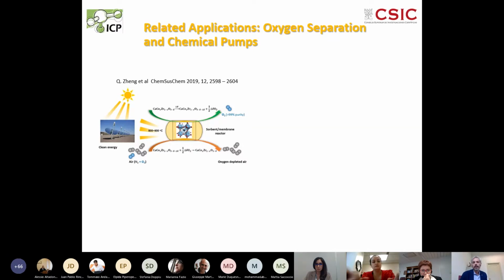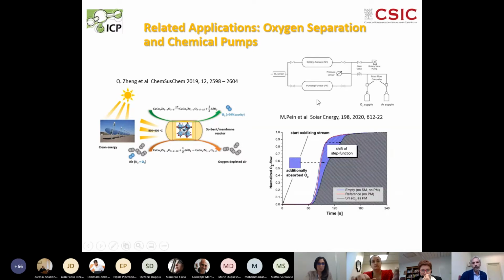And we can also take advantage of what are called chemical pumps. That is a way of shifting the equilibrium for the production of solar fuels. So we can use that, taking the oxygen, although it's not active for the production of solar fuel. And this is taking the oxygen in excess, so it's reducing the pressure and shifting the equilibrium. In that way, we can get additional efficiency. So I think this is going to be interesting in the next years for improving this material: this combination of two processes, thermochemical storage with solar fuel production.